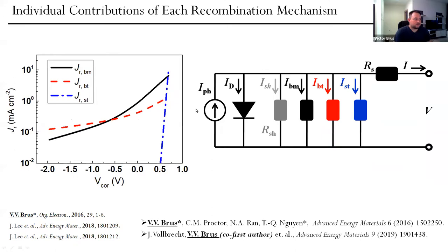When we have such a model, we can analyze the recombination contribution of each mechanism separately. And for instance, if we check the recombination current originated from surface recombination at the interface, this guy becomes important only at voltages, at forward biases close to open circuit voltage. So we see here that surface recombination will have a dramatic impact on open circuit voltage. However, at short circuit current, when we have zero voltage, it's negligibly small. So it exponentially increases with forward bias.